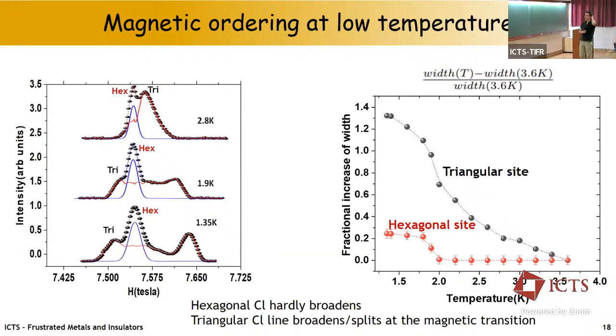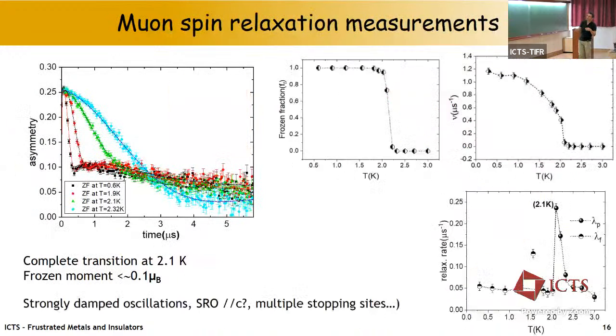Yeah, I think it comes from both. We have a strong applied external field of 7 Tesla, which polarizes. For instance, in the susceptibility, we see that this cusp is smeared out when we apply a strong field. And the nice field-cooled, zero-field-cooled bifurcation that we have at low field in susceptibility is smeared out at 7 Tesla. But probably correlations start to build up around 5 Kelvin. Around 5 Kelvin, you have this bifurcation of the field-cooled and zero-field-cooled. The muSR, I can show it here maybe.